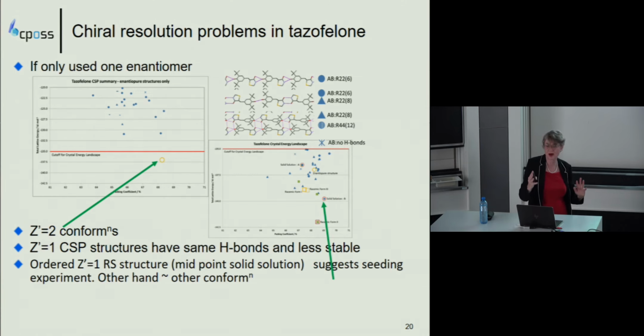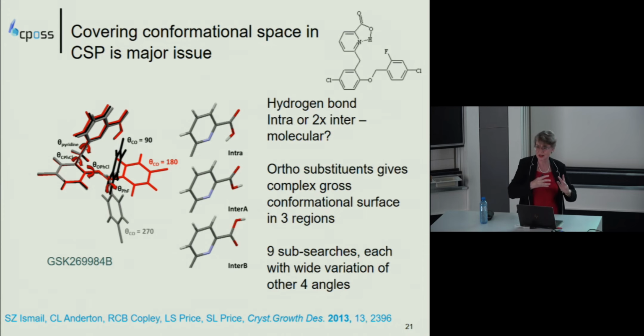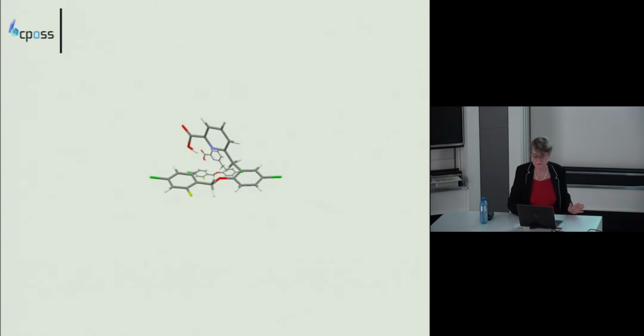Okay, this one was done with GSK, but I just wanted to include it to illustrate you've got a lot of diversity in the conformations. Yep, for this fairly simple molecule, you've got 3 different possible hydrogen bonding positions, and you've got a lot of very flexible rings, and you can see for this one case where there's sort of three different areas for that area, you can imagine once you've packed the crystal, you're going to have problems rearranging it. So essentially we did 9 searches varying the other torsion angles there. And we were delighted that the one crystal structure that they knew of came out as the lowest.